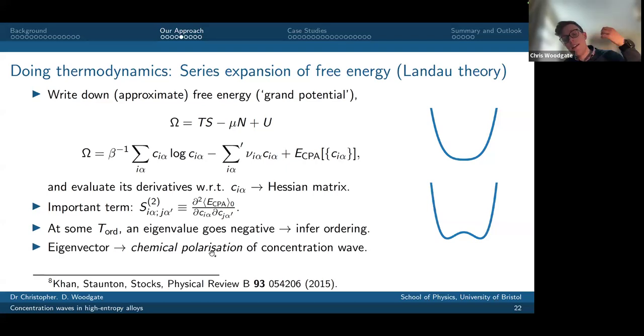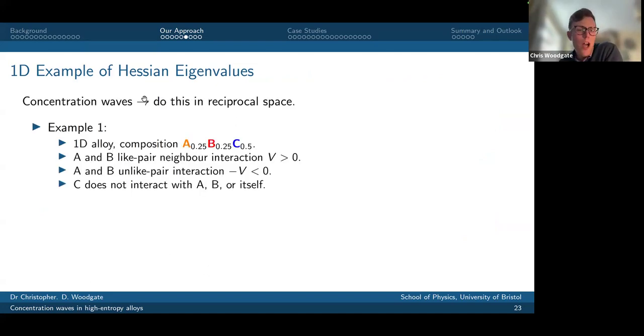Okay, and the nice thing is that in a sense, the eigenvector associated with the eigenvalue of the Hessian that's gone negative is telling me about the chemical polarization of the concentration wave. Okay, so if we think back to those ternary examples we had, what I want to do is just show you what the eigenvalues of this Hessian matrix can look like. So we work in reciprocal space.